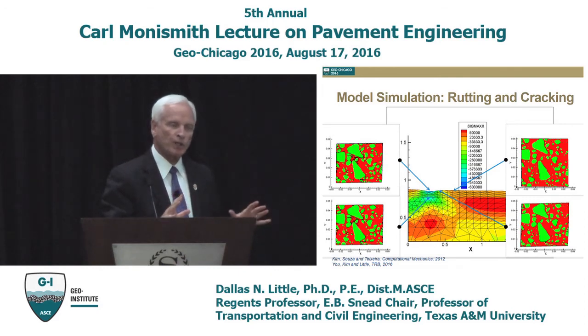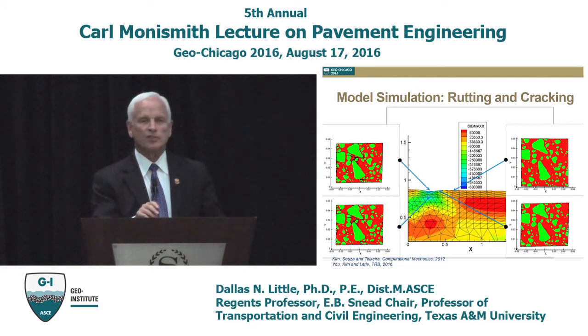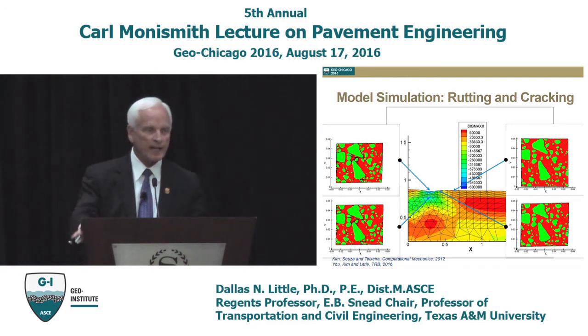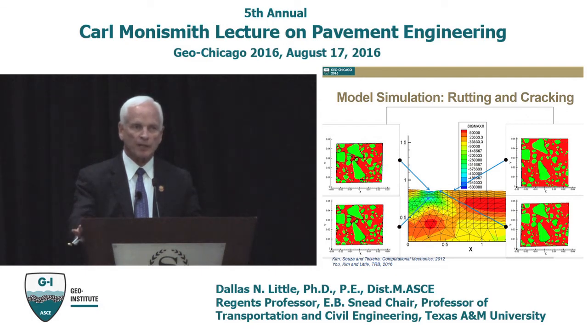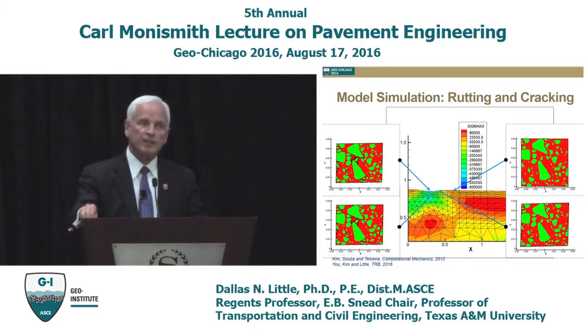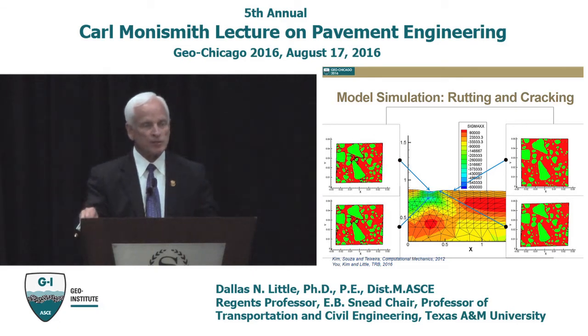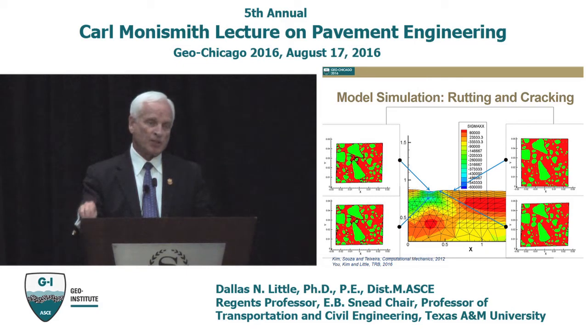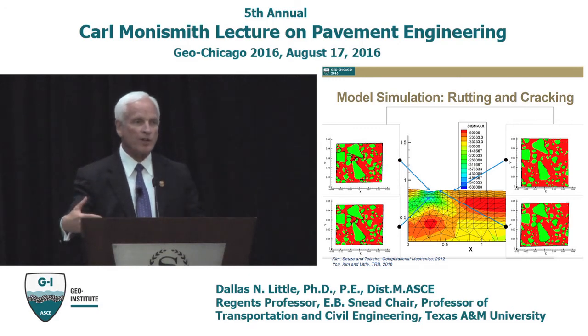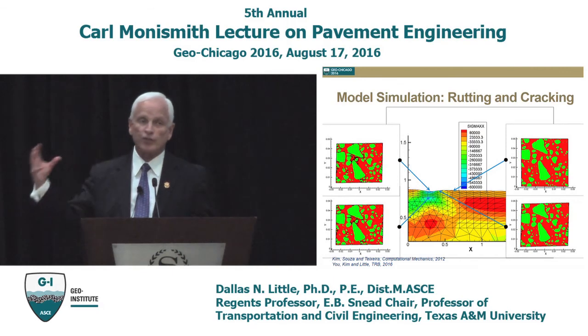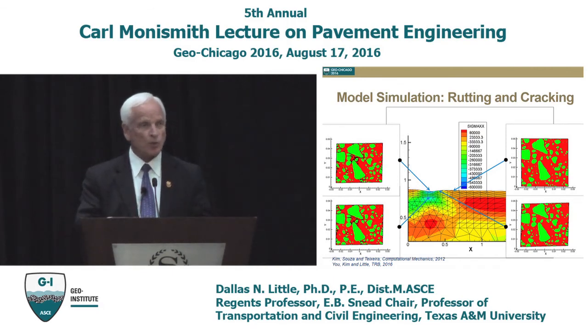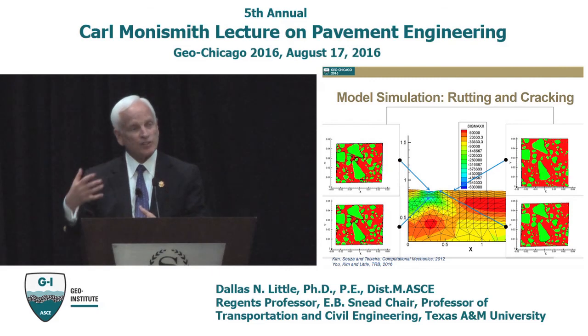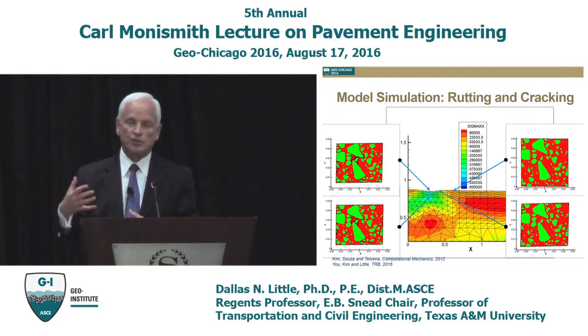But at this point in time, I want to quickly review what we've talked about so far: a template called Panda that characterizes the asphalt as viscoelastic, viscoplastic, nonlinear. Those are very important parameters. Panda is set in a template that is based on continuum damage mechanics. Continuum damage mechanics has some limitations, but its true value is that it allows us to couple other mechanisms with it. For example, moisture diffusion, weakening of the mastic, weakening of the asphalt aggregate interface because of moisture. It allows us to couple in the effects of aging, which harden the asphalt, making it more susceptible to damage.